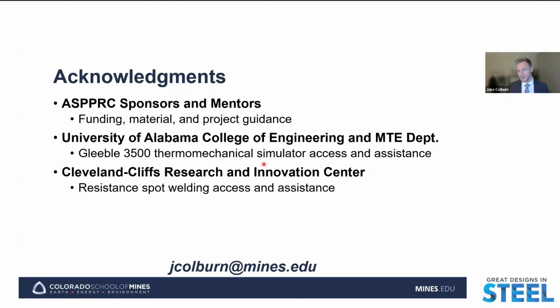Yeah, I think that's interesting. And I would say, yes, I have seen some of that copper alloying in some of the welds that we've looked at. And yes, that would be great to look at. But for simplicity and trying to focus in on some of the main factors, we're saying that potentially that copper effect may be equal across those composition ranges when comparing the high silicon, low silicon alloy, and then the high aluminum and low aluminum alloy. We would say that maybe that's a constant across those two, and hopefully there's not too much of a difference between the behavior there. But I think we have had a student at Mines that's been looking at the effect of copper content on weldability, at least in terms of resistance spot welding when looking at residual copper. And I think he also saw a negative impact of having increasing copper content in the substrate, at least for resistance spot weldability. But yeah, that's an interesting consideration to look at.